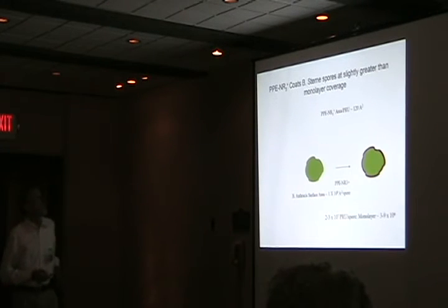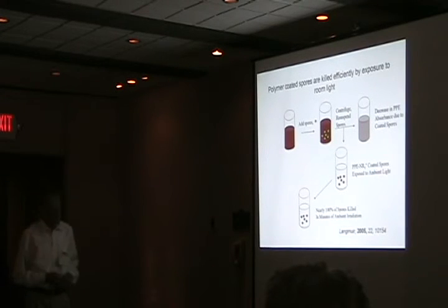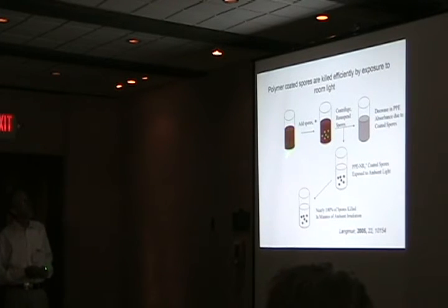We can take, for example, anthrax spores and look at the coating of the polymer on the spores just by having excess polymer present. And what we get is slightly more than monolayer coverage of the spores, and the spores are, again, very highly fluorescent. They're also dead as soon as they're exposed to visible light. So here's an experiment where we add spores to the solution of the polymer, monitor the decrease in absorbance due to the coated spores, remove the coated spores and suspend them in water and expose them to ambient light, and nearly 100% of the spores are killed with just minutes of ambient irradiation.